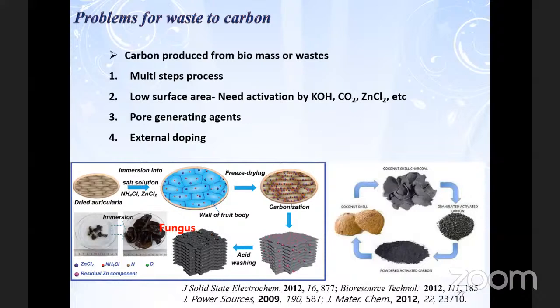Okay, and these are mostly, for example, the coconut shell is very highly rigid. You need an activation. You need to break it. It's very hard. You need to break it, so it will increase the pore structure and surface area. And the activation method is mostly carried out at high temperature using KOH, CO2, or zinc chloride. And also you have to put the pore generating agent.